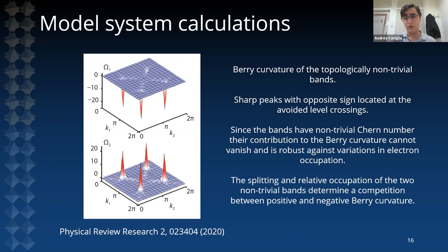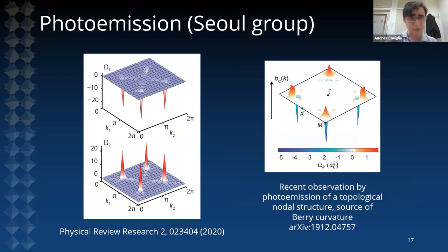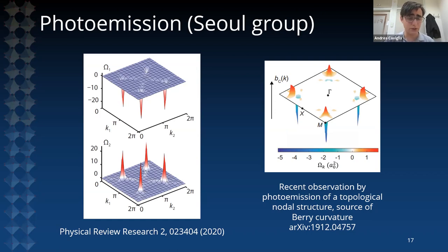This is a very robust effect because it's derived from bands with a non-trivial Chern number, so variations in chemical potential are not going to affect this phenomenon much. However, interfacial effects can act on the symmetry breaking and the magnitude of the level crossing behind the Berry curvature, determining the competition between positive and negative contributions. Recently, a very nice photoemission study from the Seoul group showed that these nodal structures are indeed also observed in ARPES, confirming we're on the right track.